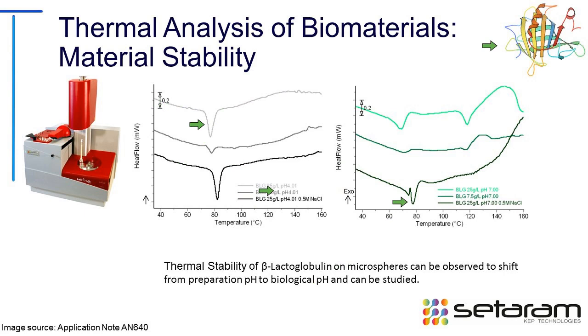experimentation was done at a pH of around 4, which is the preparation pH for appending these beta-lactoglobulin proteins. But when we shift to a more biologically relevant pH, around 7, we see a dramatic shift of the stability of this protein down to around 60 or 70 degrees. And we see the apparent instability of these proteins once we even start adding some media proteins in, or just salts as part of tissue culture. So this is part of the reason why it's incredibly important for us to measure biological materials in their native environment or in more cell culture type of conditioning, because we can see dramatic shifts in the thermal stability just due to the inherent switch of a biological from more of a preparatory to a biological pH.